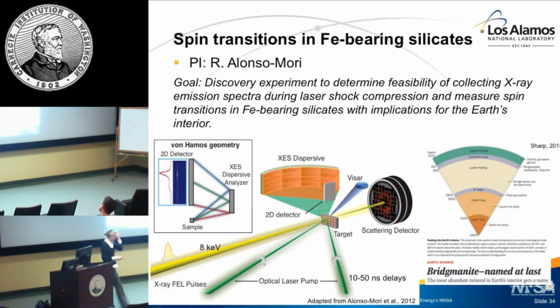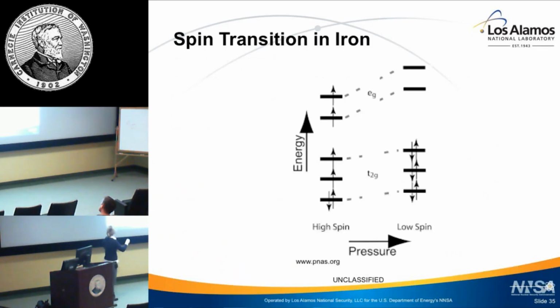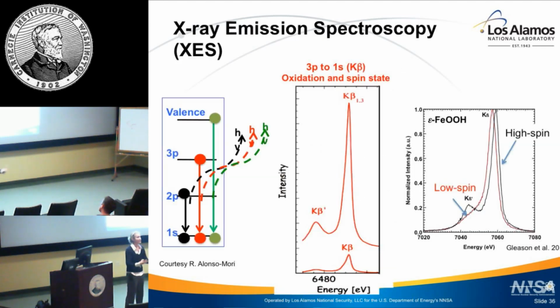I want to talk about that for just a moment. If you look at the last unfilled electronic orbital, this is an electronic fine structure of that last orbital, wherein we're looking at the splitting, essentially the eg to t2g transition, going from a high spin state to a low spin state. It's more energetically favorable at higher pressure to go into a low spin state. In this emission spectroscopy, we're really sensitive to oxidation and spin state. There are other kinds of spectroscopy techniques we would want to test, and those are not yet technically achievable. So this is one that we could do.